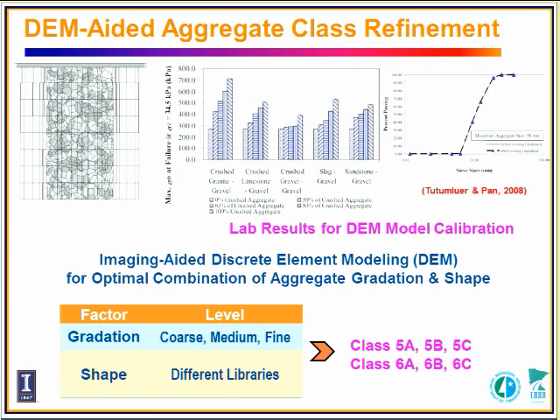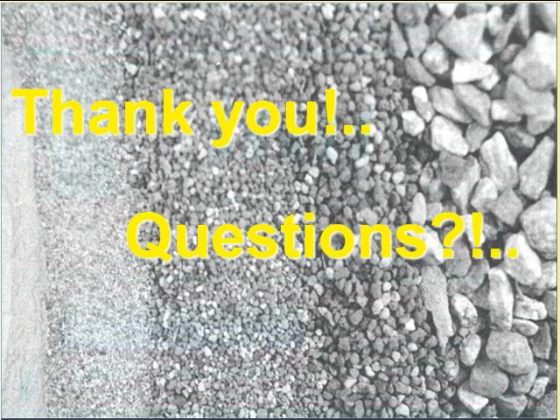Another thing we are working on now: because we identified this parameter mainly from experimental investigation, we are still in the stage of further validating this framework. So we pursue the discrete element method. We already have a well-established database from 2008, completed by Professor Tutumluer and his student. This study investigates 6 different types of aggregates, with just one gradation and different shape effects. We hope to calibrate the DEM model parameters using this database. Once the DEM model is calibrated, we can use it to study different combinations of shape and gradation to further redefine the current MnDOT specifications. With that, I would like to thank you for your attention and welcome any questions.